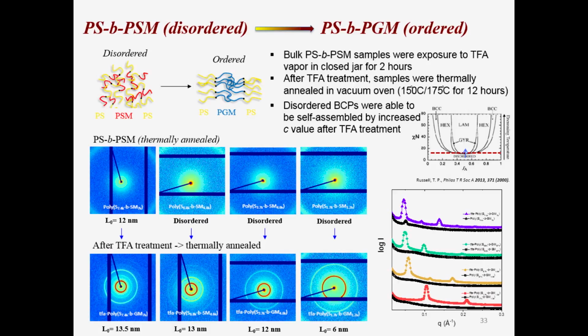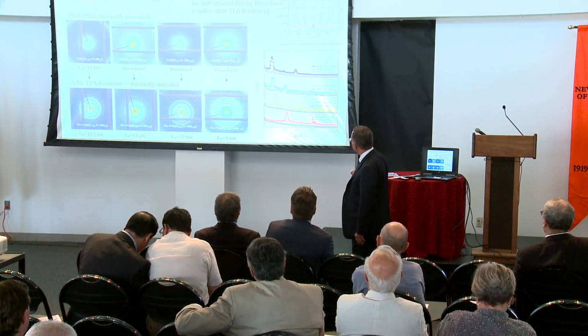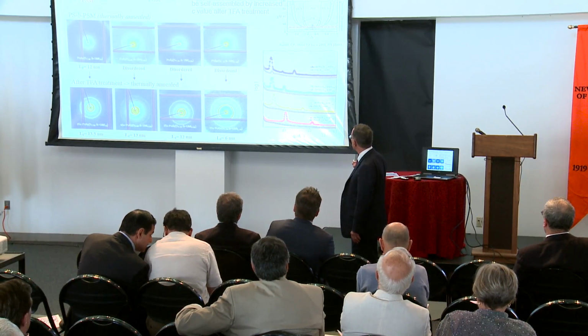And so what that allows me to do is to cast a thin, nice uniform film, and then be able to convert the system. So I start off initially, these happen to be scattering profiles, with the film being in this disordered state. I expose it to the trifluoroacetic acid, and I push it into the phase-separated state.